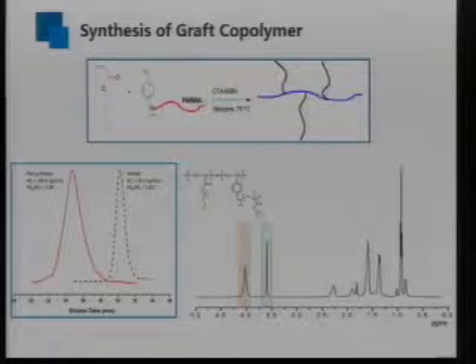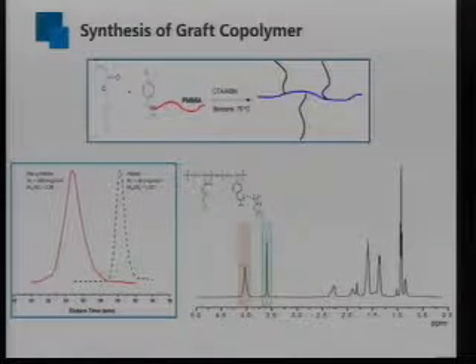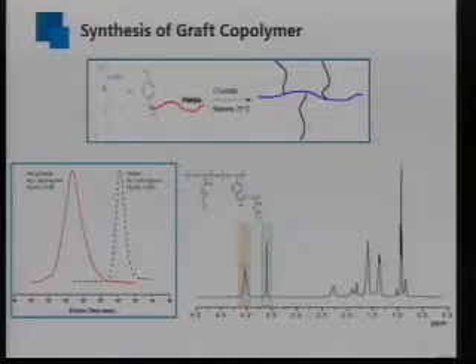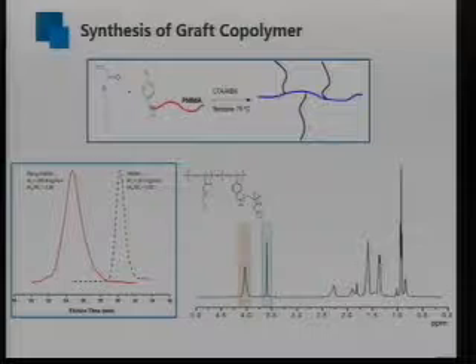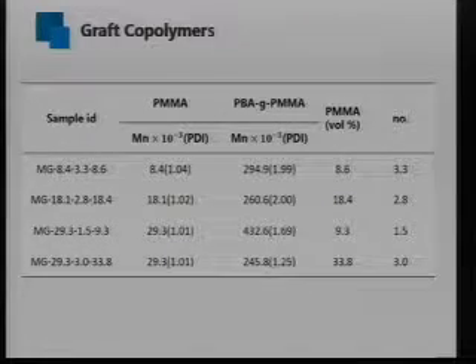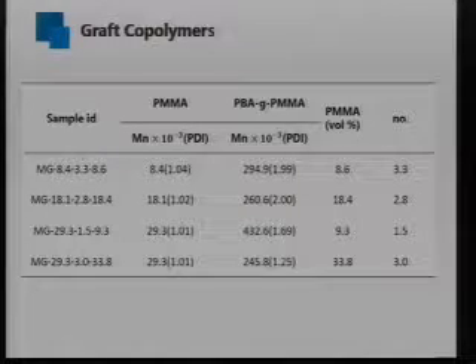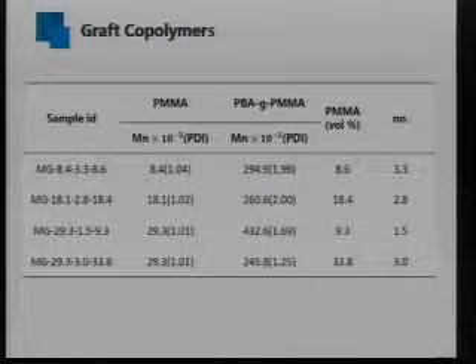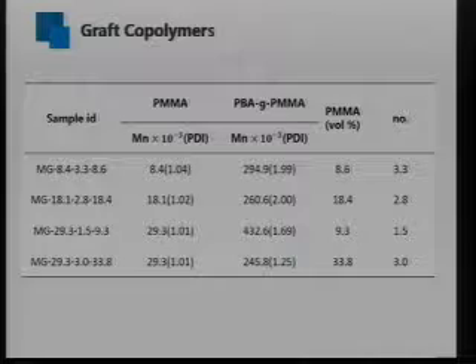with even no remaining of the macromonomer. And the composition of the butyl acrylate and MMA blocks was determined and calculated by proton NMR. And 4 different polymer samples were synthesized with different molecular weights of PMMA side arms and different volume ratios.